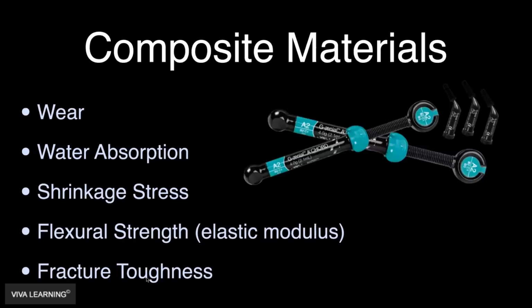Flexural strength, or the elastic modulus of a material. We actually like materials to sort of have a similar elastic modulus to real tooth structure, so they can bend and flex and move with the tooth, which means that we're not putting stress on the adhesive interface, and therefore we're not causing that adhesive interface to degrade or break down, or the restoration to fall out. And then fracture toughness. Obviously, we want materials that don't fracture, right? So lots of great physical properties of composites that are important to us.